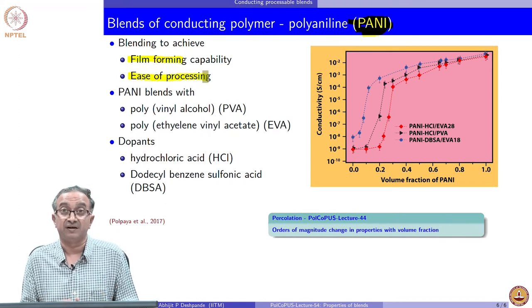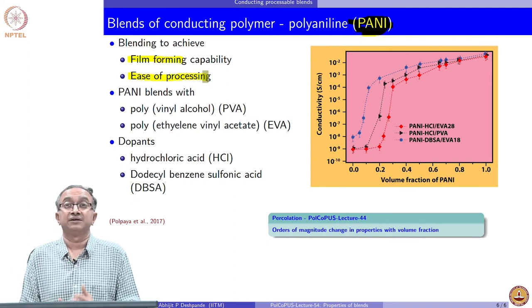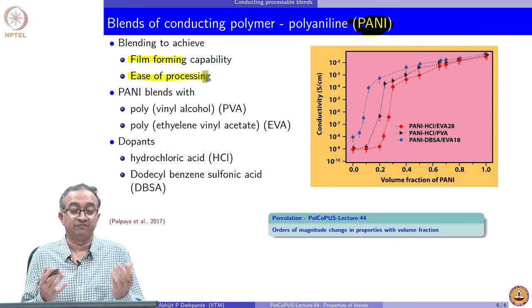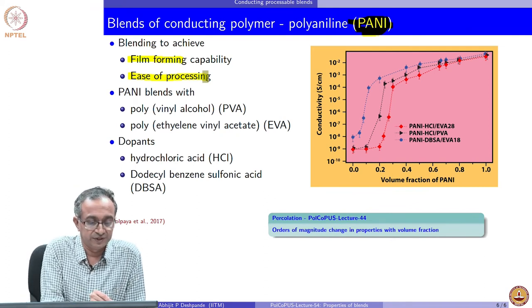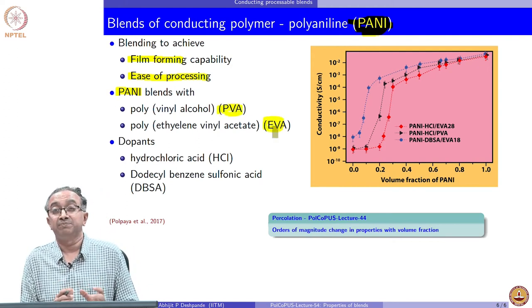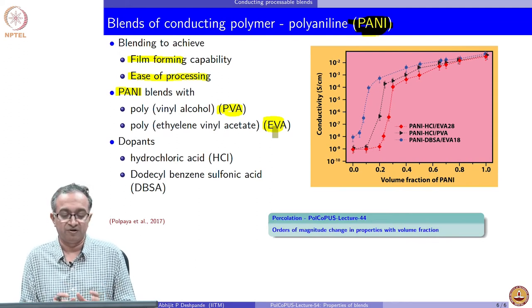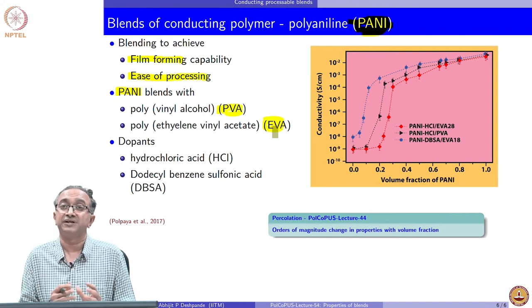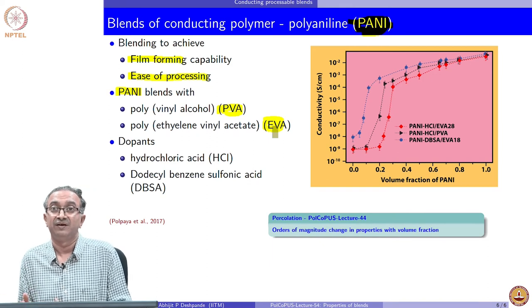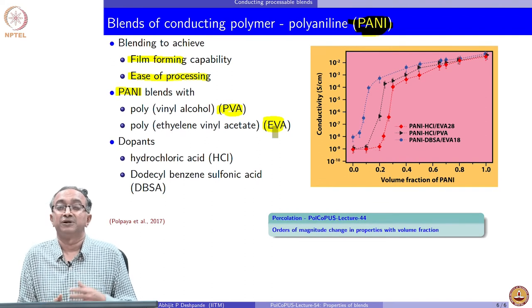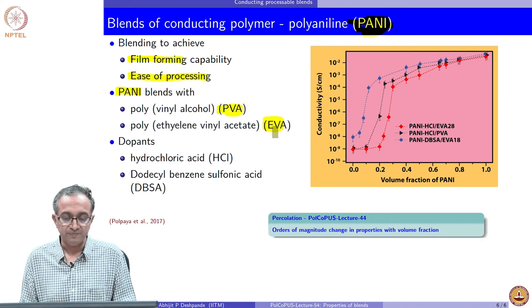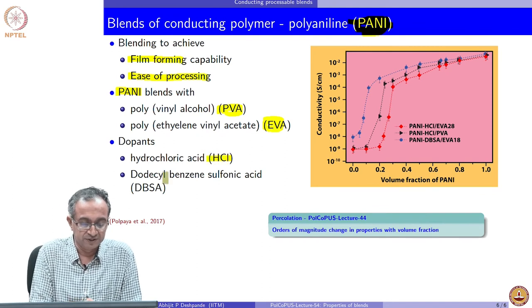Given this, can we blend a conducting polymer, which is very useful for certain sensor, actuator, semiconductor applications, but we cannot use it because of processing difficulties as well as film forming capability is limited? You can blend PANI. In this case, what we will look at are examples of blend of PANI with two insulating polymers. Both polyvinyl alcohol and ethylene vinyl acetate are being incorporated in the blend because of their flexibility and mechanical performance and film forming capability and ease of processing. While PANI is the material which gives us the conductivity. But because its processability is difficult and because its film forming capability is poor, we need to blend the two. In conducting polymers, we also use the dopant. Therefore, different types of dopants can be used.